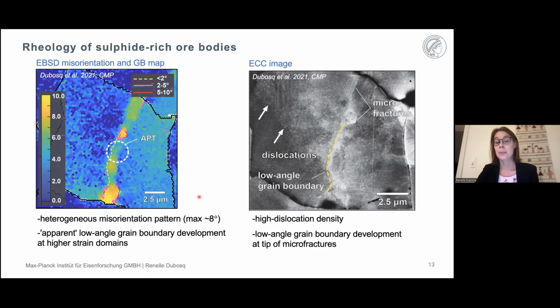Now I say apparent because if we turn our attention to the ECC images, we notice that these low angle grain boundaries are in fact microfractures. And so this is shown here by these very discrete line segments. So these are not low angle grain boundaries. However, if we look at the tip of these microfractures, we notice that there is still dislocation walling, which are mostly propagating from these microfractures.